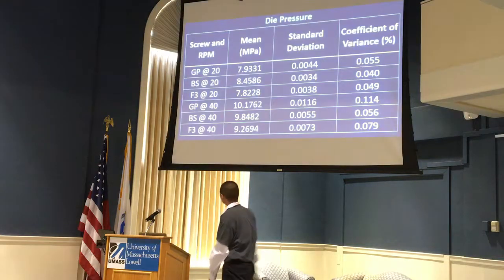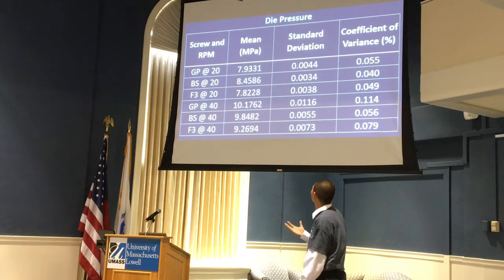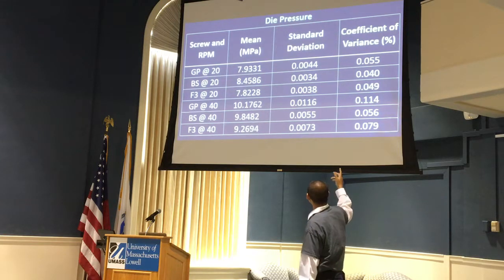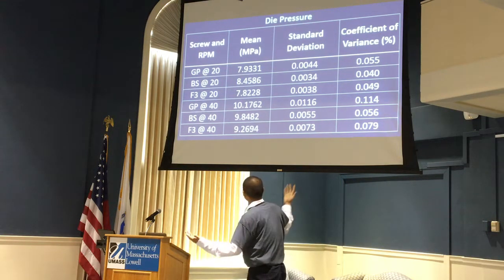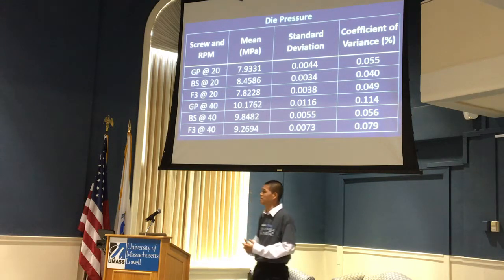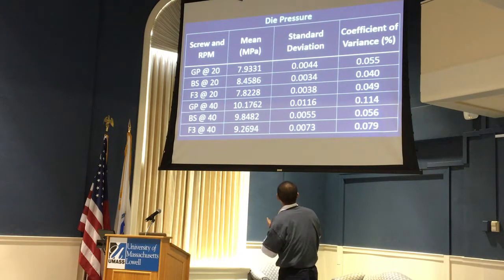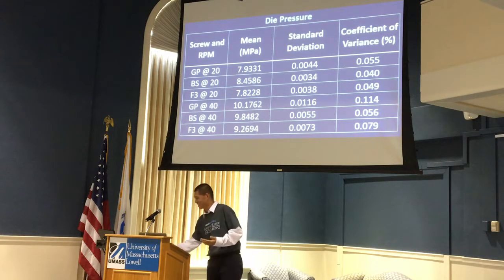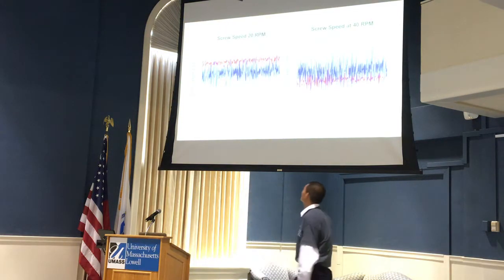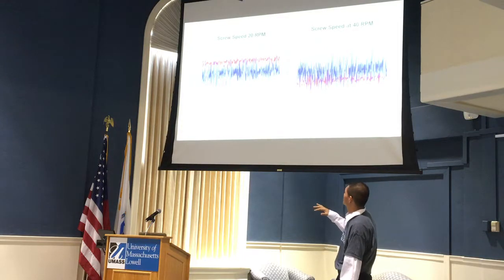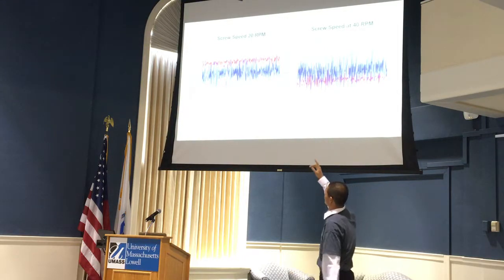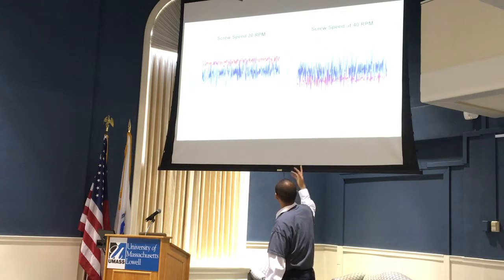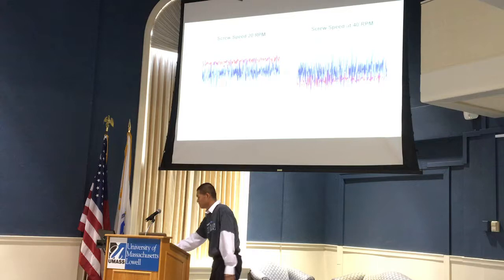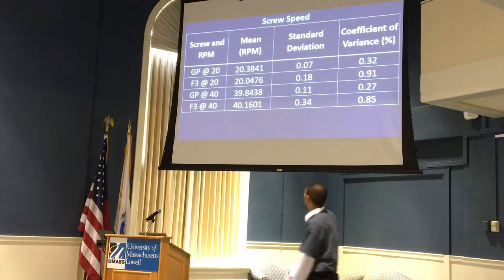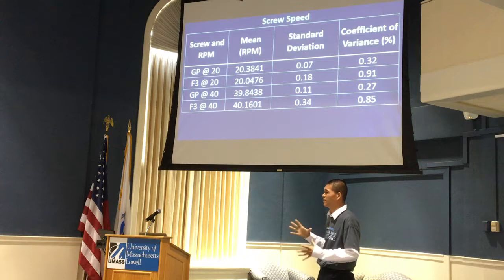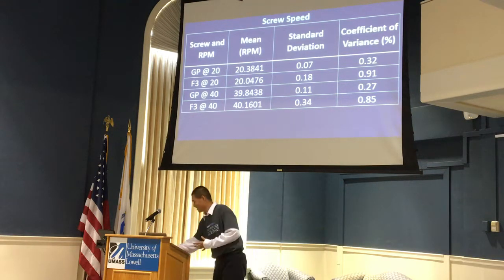So again, it's very inconclusive, but it is right to say that our coefficients of variance, our relative standard deviation, is very, very small. It's in the hundredths, and it's even in the thousandths, so it might not be very significant. In terms of screw speed, we compared our general purpose screw and fractal screw. You see a lot more noise, or a lot more waves, in our blue line, which is our fractal screw. And we again see that the general purpose screw performed better in theory and might have caused less surging.